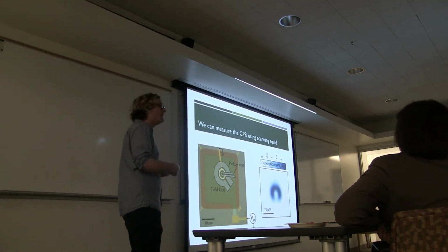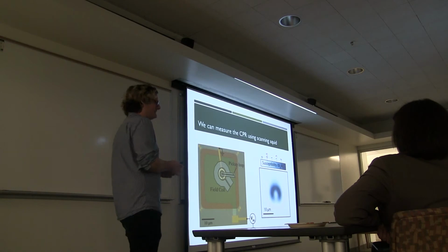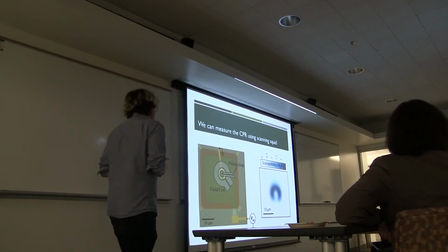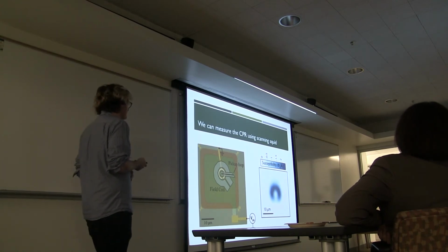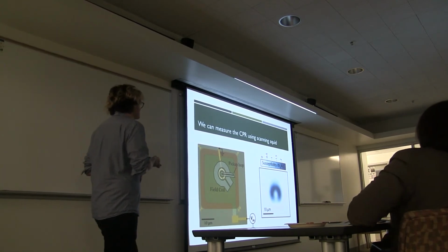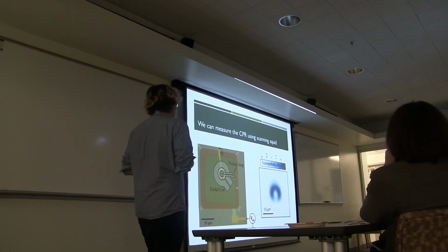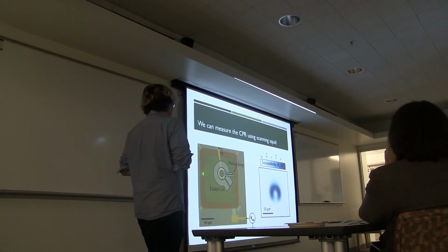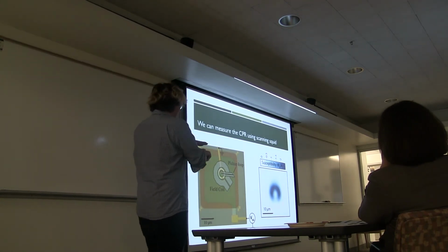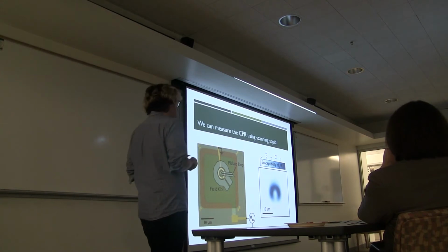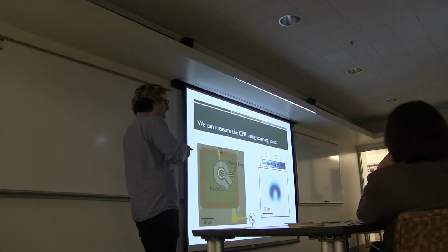So that allows us to tune the density of electrons in the nanowire, and look at how the current phase relation changes as a function of that. We're able to image many samples because not only can we see the current phase relation by the circulating current, but we can also see the diamagnetism, or the repulsion of magnetic fields, due to the evaporated aluminum ring. And so we can navigate by looking around for these ring features, and then center the SQUID over them so that we can measure the currents.